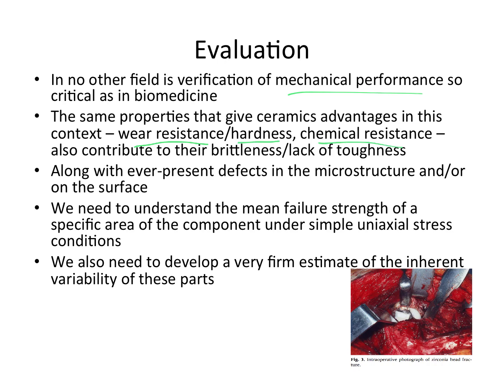Alumina lasts in the body. It doesn't really do much to it. All those things also make it very flaw sensitive, because of the presence of defects in the microstructure or on the surface, as we just saw. And we need to get some idea of the mean failure strength of a component under stresses. Let's call it uniaxial stress. And we also need to, very importantly, develop a very firm estimate of the inherent variability of these parts.